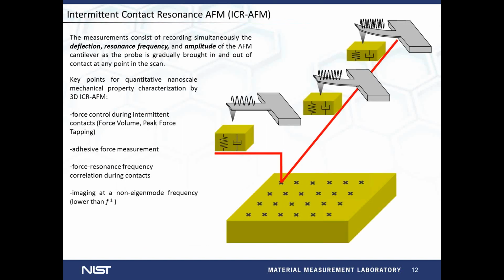One immediate extension of this load-dependent CRFM measurement is to perform them in an array distributed over the scan area, in which case we end up with a new scanning mode, namely intermittent contact resonance AFM. And the idea is that the volume of this data will provide the three-dimensional characterization of the nearby subsurface mechanical properties of the material probed. And not negligible, it is also the fact that, being operated in an intermittent contact mode, the tip is better preserved during scanning than in contact mode. Here is shown an implementation in force volume.